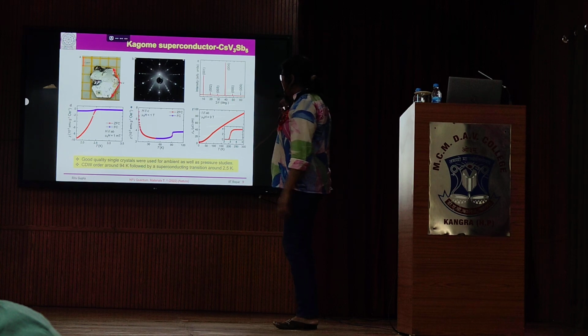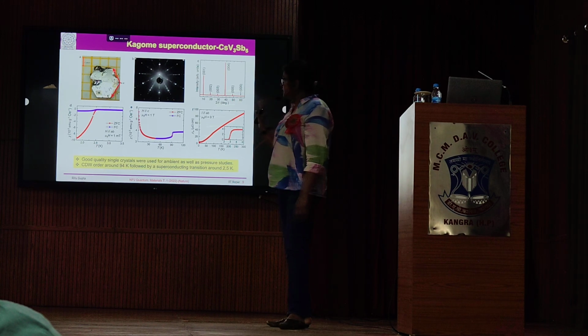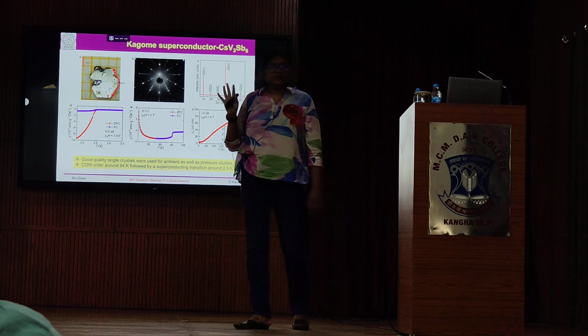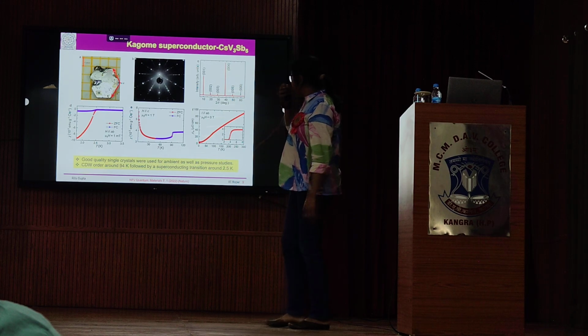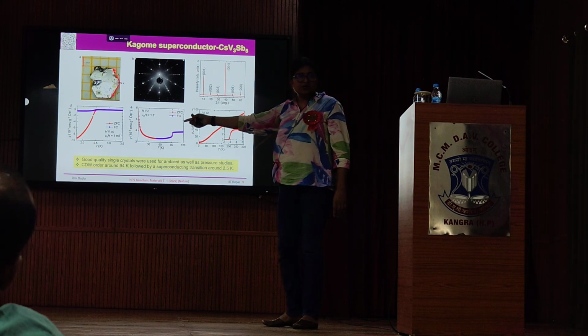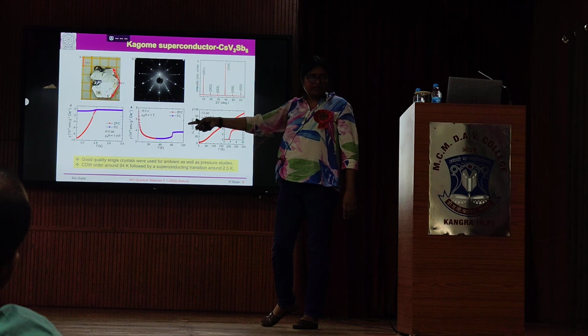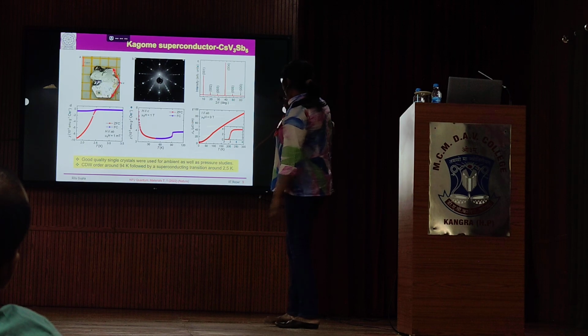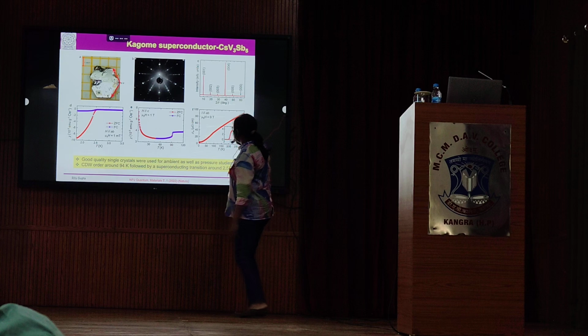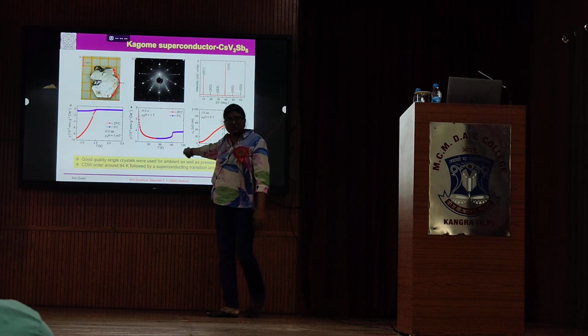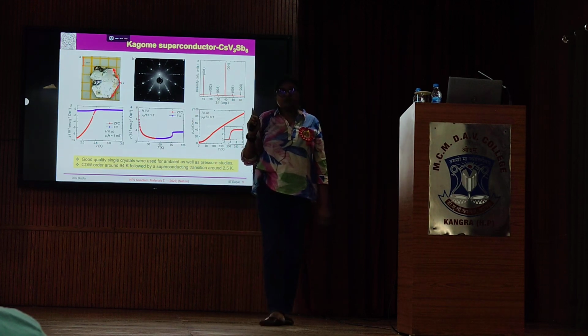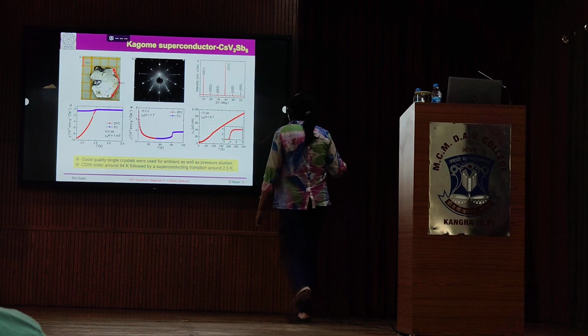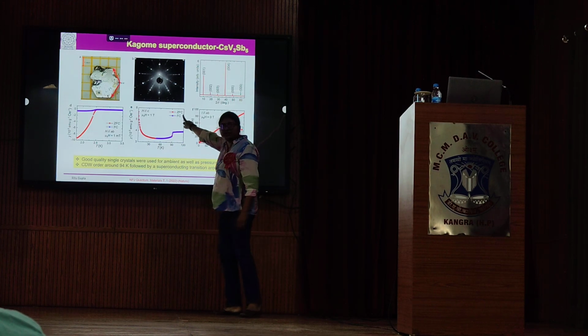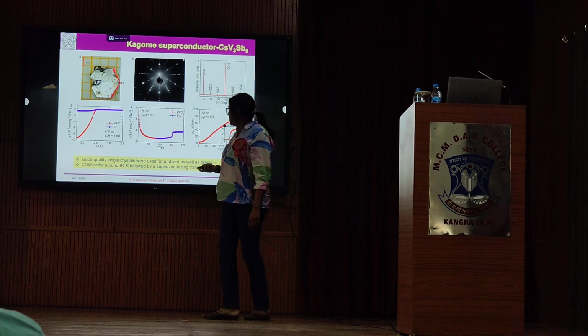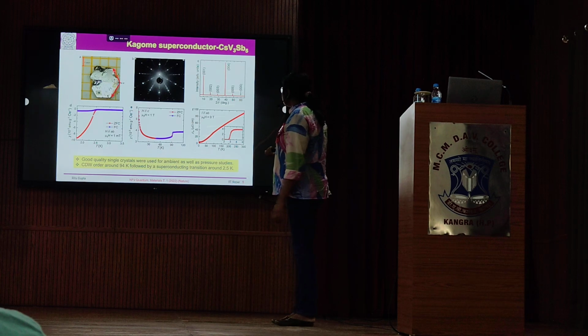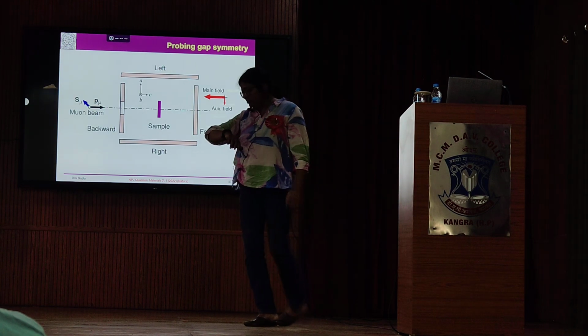Okay. Then you do the magnetization measurement, chi versus T. You have heard that a superconductor is a perfect diamagnetic material. So this is clearly visible from here. You can see chi versus T is going in the negative direction below 2.5 Kelvin. Okay, and you can also look at the resistivity here, which goes down almost to 0 below 2.5 Kelvin. So it has a TC of 2.5 Kelvin, and there is a charge density wave transition at around 94 Kelvin, which can also be seen with certain features here. Okay. So now we want to probe the gap symmetry of this compound.